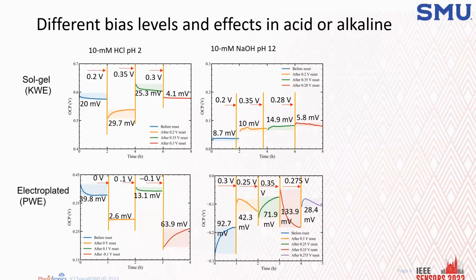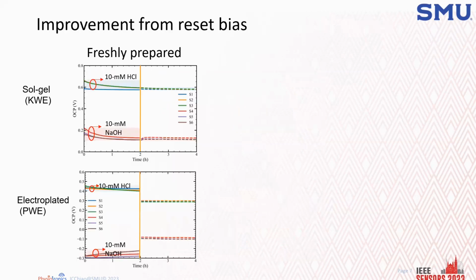For alkaline, for the sol-gel process, we found that 0.28 volts gives the best drift performance. And then when we tried this for electroplated, as expected, because one is anhydrous and one is hydrous, the performance was completely different, but yet we found 0.275 volts probably is the best drift performance. So then we decided, okay, maybe for acid, we should have 0.3 volts reset, and for alkaline, we should have 0.28 reset. And then we start our experiments.